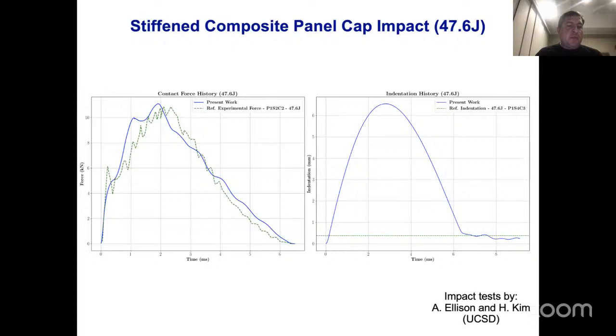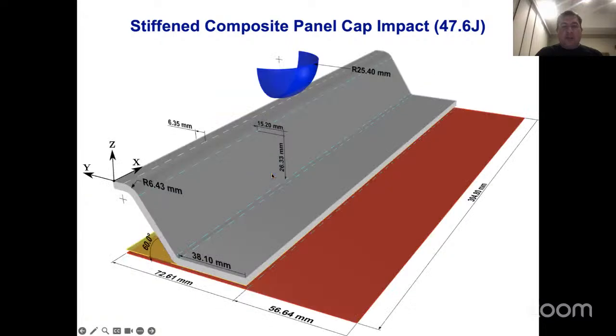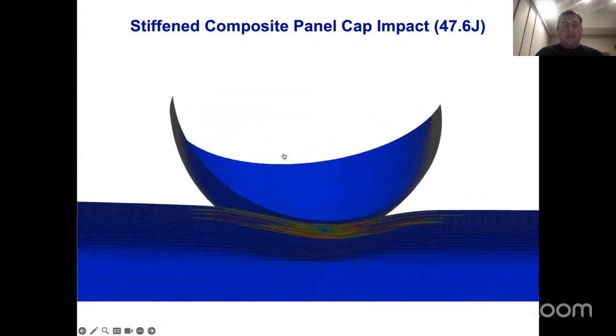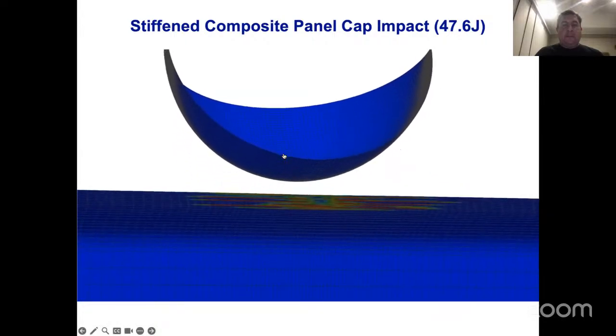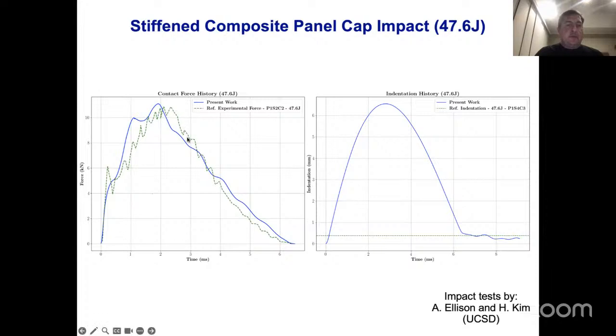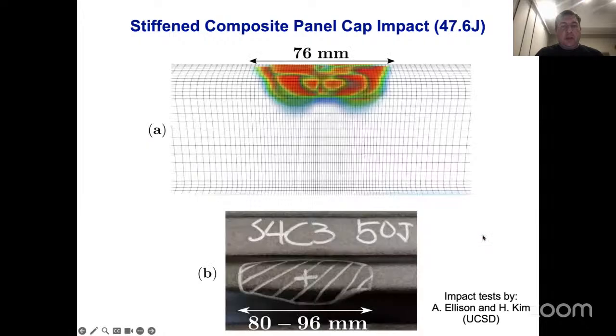when it comes to impact on plates, the boundary conditions in the experiments are not very well characterized. So in this case, you can see all the action takes place away from the boundaries. Because the problem is less sensitive, we can actually capture the forces much better. And also, our experimental colleagues reported indentation size, and it looks like we're capturing that pretty well also, which is very good.